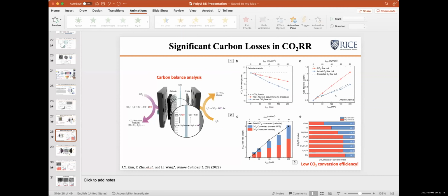But of course, as Lanshu just mentioned, there are still challenges regarding membrane stability. Also, there are challenges with carbon crossover, for which we recently published a paper to specifically address that, but we know this is not the only solution, and many more solutions will come out. So there are still issues. Stability is a big issue, but also the one-pass efficiency. Let's say you have a CO2 stream coming in. If your conversion is only 10%, how can you convert the remaining 90%? That is relevant to carbon crossover loss. And if you slow down your CO2 flow and reach 80% conversion, how can you maintain that high selectivity? So there are still some practical issues when testing in MEA studies.